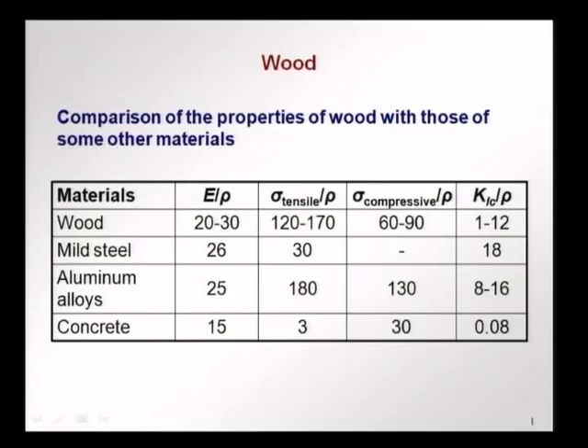Let us compare the properties of wood with some other materials. In this table, what we have done is looked at 4 different properties with reference to the density. So, the materials that are compared are wood, mild steel, aluminum alloys and concrete. In the first column, we have the Young's modulus divided by the density, or the elastic modulus normalized with the density, and you find that wood has a value of 20 to 30, same range as mild steel and aluminum, and better than concrete, which is obviously much heavier.